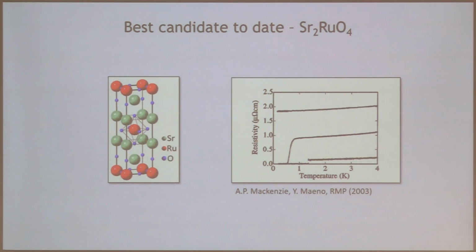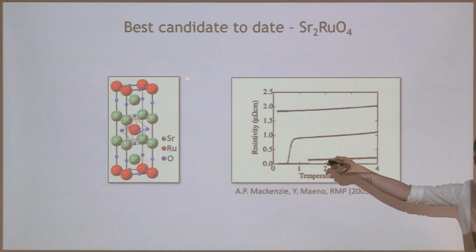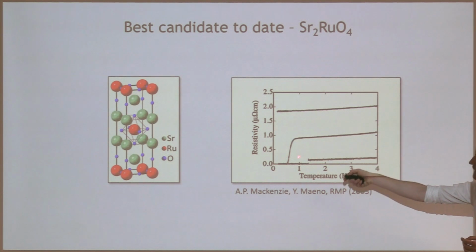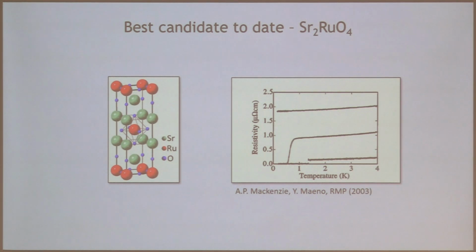Now, I don't know how many people here know about metals, but if you're a metals person, that's a really clean metal. And it wasn't until they got that down to a few tens of hundreds of nano-ohm centimeters that you really reach the maximum bulk TC. This is a crazy sensitivity to disorder. And there's reasons that P-wave superconductors, because of the way, at least for this particular one, the way the gap structure occurs, are particularly sensitive to disorder.